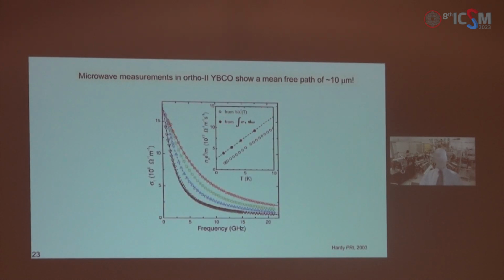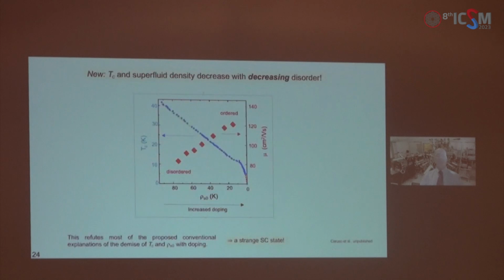And we are not alone in this. Here are some quite spectacular microwave data from Walter Hardy's group, 2 decades ago, on an extremely clean ortho-II YBCO crystal. The relaxation rate measured here is less than 3 gigahertz, which is something like 10 micro-electron volts. And that means that the inferred mean free path is of the order of 10 microns. That's extremely clean by anyone's standards.